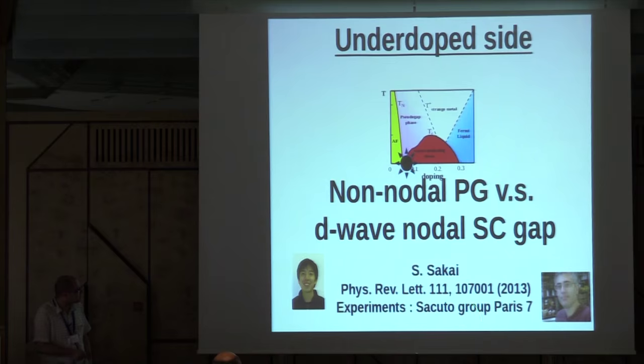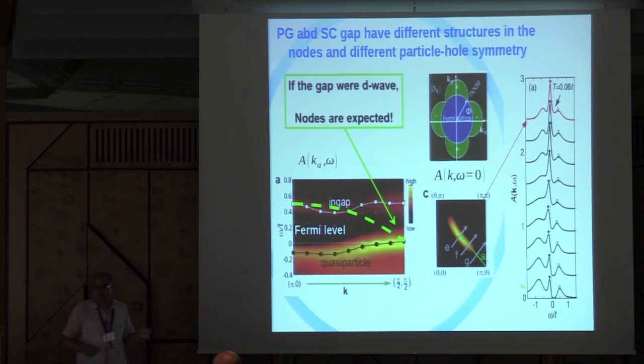Let me just present the first result in the underdoped case. This is work done thanks to Shiro Sakai, who has developed the continuous time Monte Carlo. And we collaborated with a group in Paris who do Raman scattering. So we looked in detail at the structure of the pseudogap, thanks to the 16 site cluster. Now we start to believe what we were seeing. And we compared it with what is expected to be the gap in a d-wave superconductor. So, coming back to your question about how I should see this pseudogap, this is like ARPES spectra, if you want, only calculated with CDMFT.